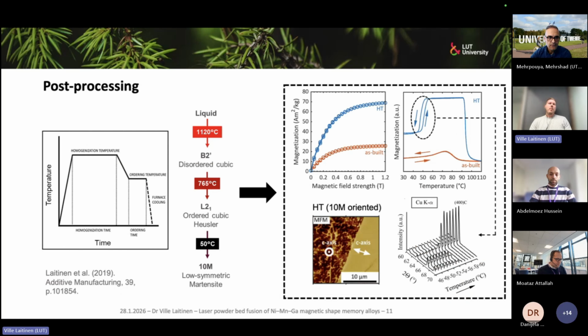Now, from a nickel-manganese-gallium material point of view, we need some post-processing steps, the first being heat treatment. After the laser powder bed fusion itself, we have a huge amount of atomic disorder inside the material, and in order to recover magnetic properties especially, we need to do a high-temperature heat treatment where we get these atoms in the right places so that we have a long-range order in our atomic lattice.